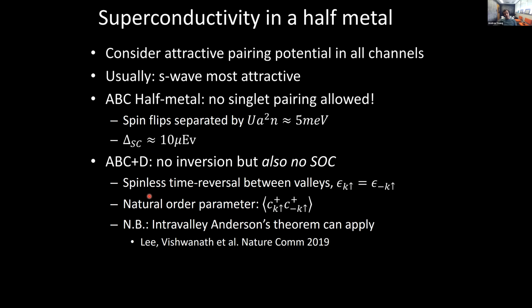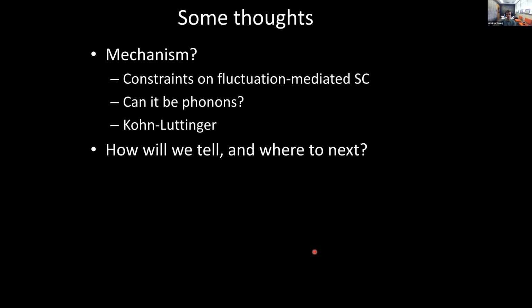But in graphene, that's actually rather special because in addition to not having inversion symmetry, as often happens in ferromagnets, and therefore no obvious pair that's degenerate, we also don't have spin-orbit coupling. And so what this means is that you can have spinless time reversal symmetry between electrons in the different valleys. So that's a natural way to then make a superconductor: just forget about spin and call valley our new spin, and then you have a superconductor where you pair states of opposite momentum in opposite valleys, right? And those are sort of guaranteed to be degenerate by the absence of spin-orbit coupling. And in this situation, you can actually get something that would be a spin triplet, but valley singlet superconductor. And in many ways, it would be rather similar to a conventional superconductor. So that might be what's happening.